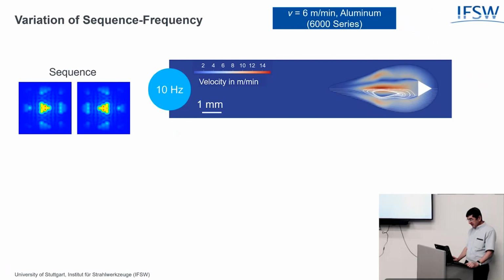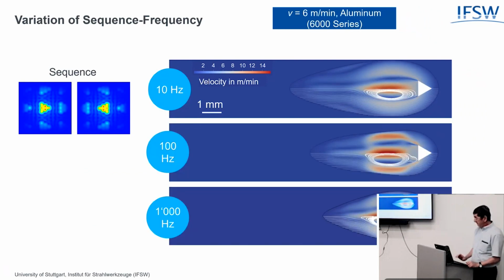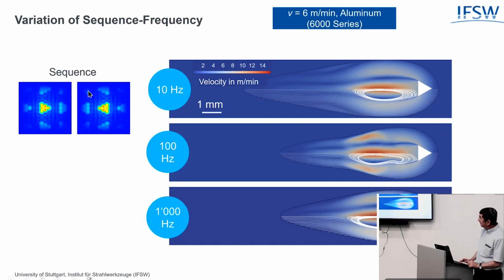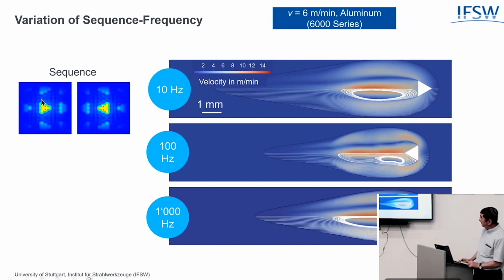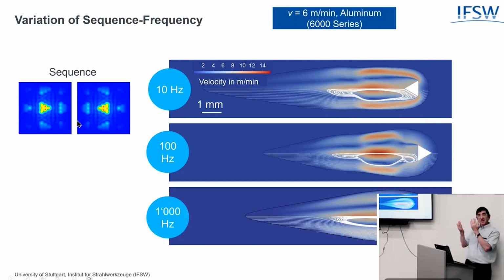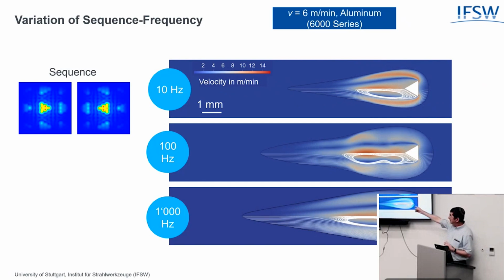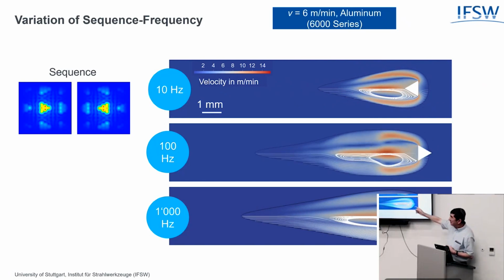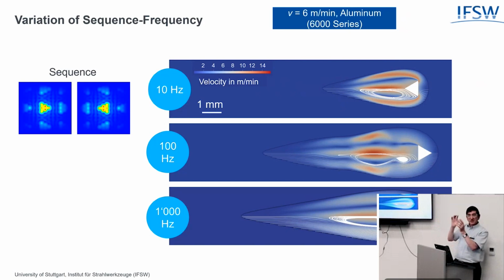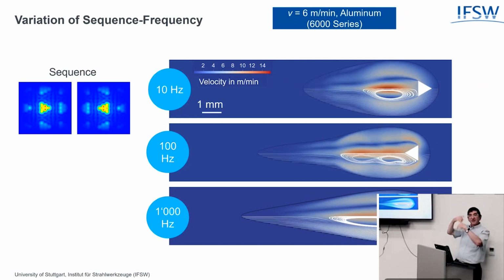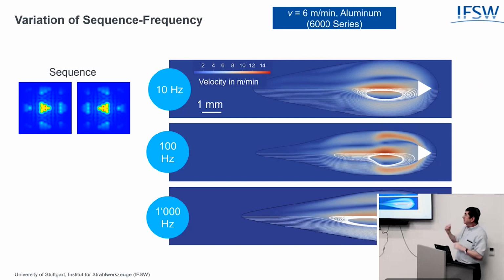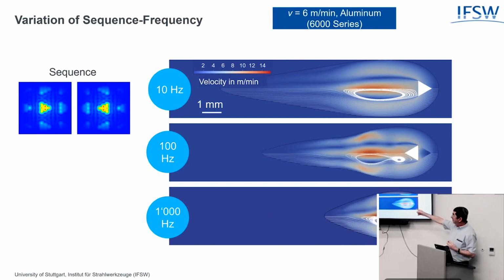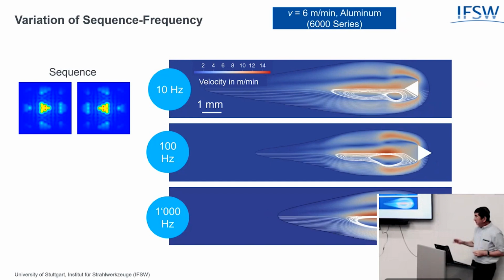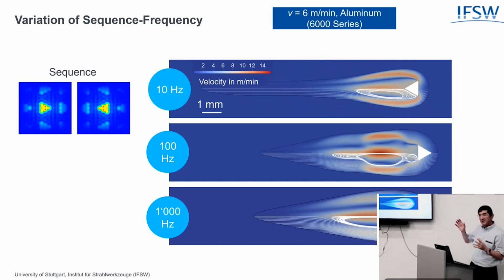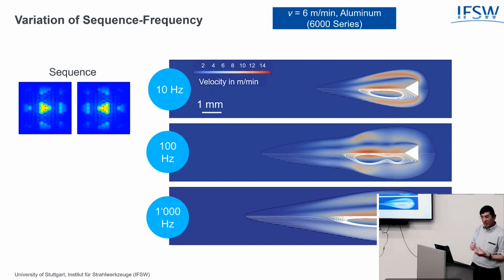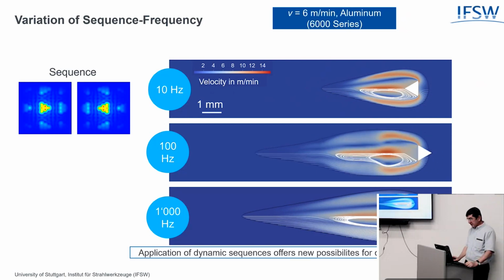IFSW designed something else. They designed these 2 beam shapes here on the left, and they switch between them. And when you switch between them, you can see here they switch at 1000 hertz, meaning switching between the shapes. Each shape by itself is dynamic and moving at a much higher rate, but switching between the 2 shapes, if you do it at a kilohertz or 100 hertz or 10 hertz, you can see in the simulation how you have completely different flow inside the melt pool, and you get completely different results from each type of these welds.